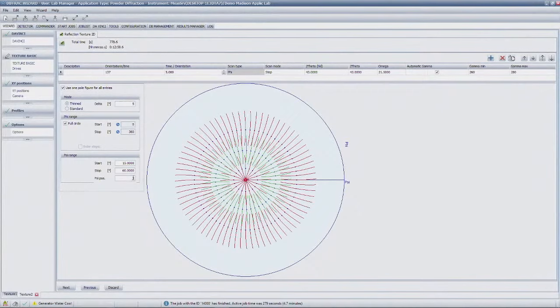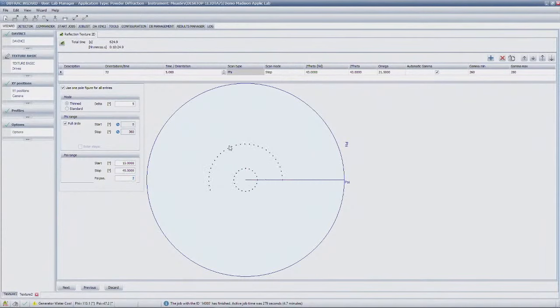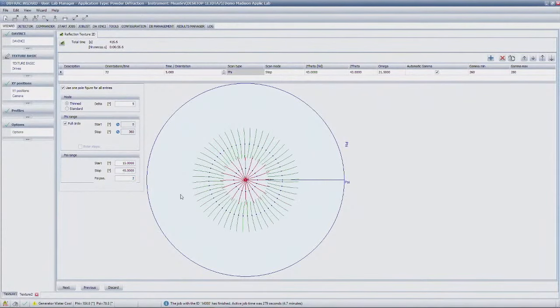So maybe we wanted to do, say, 15 to 45. We could do, say, 2. And you see it dynamically updates to indicate how much of that sphere you're covering. And so here, if we go from, say, 15 to 45 psi, we can cover this in just 2 separate frames. So one at 15, one at 45, and we're able to fully fill in this map. This is going to be right now about a 7-minute pole figure, which is really remarkably fast.